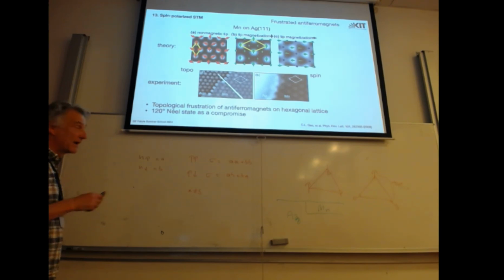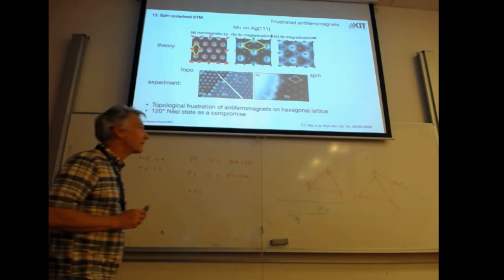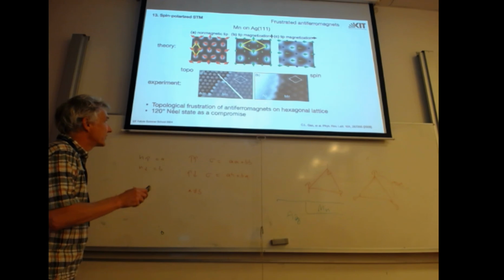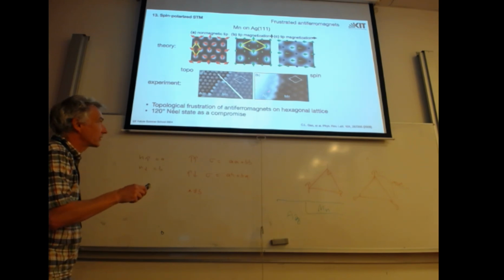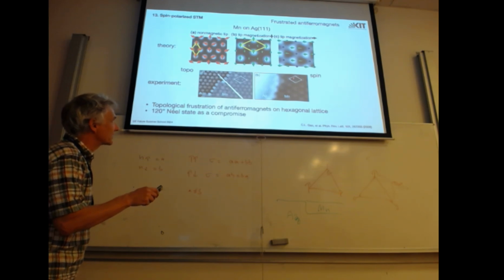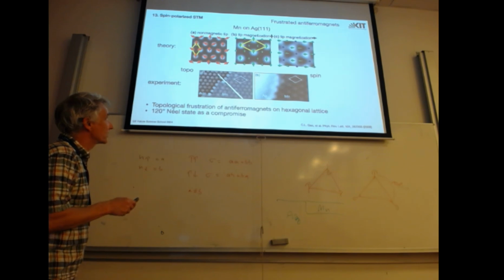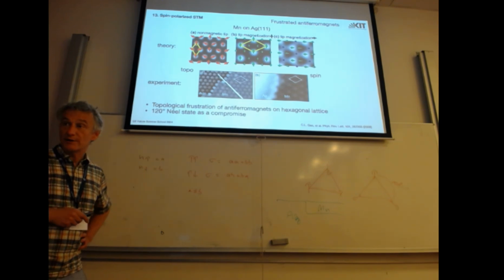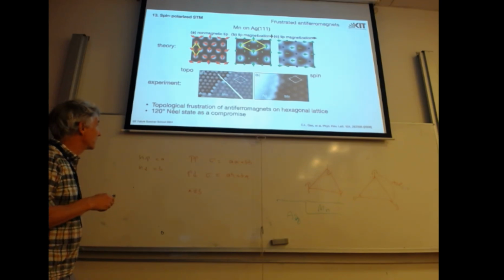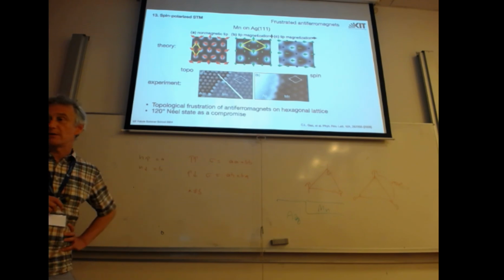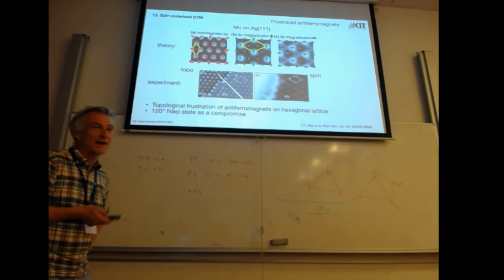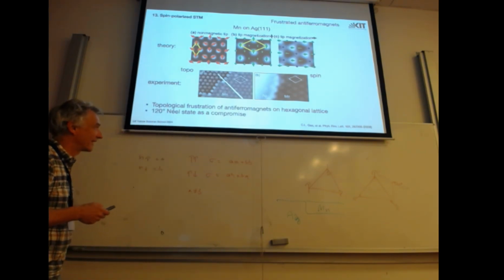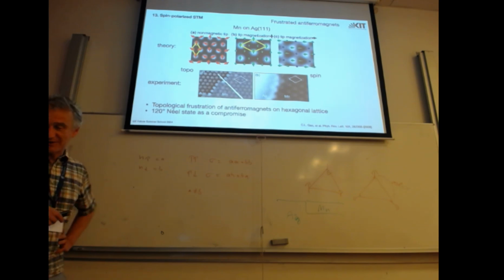We see every manganese atom in topography, and they are slightly different heights, so we can see this contrast between manganese and silver. Now we do the spin polarized STM, so this microscopy, we map this. Silver is unpolarized, has some kind of differential conductivity, and the manganese, you see, gets a new size of unit cell, which is this unit cell here. So we actually see that indeed this is the 120-degree Néel state. This is the first image of any Néel state in this case. At that time, it was a big thing.